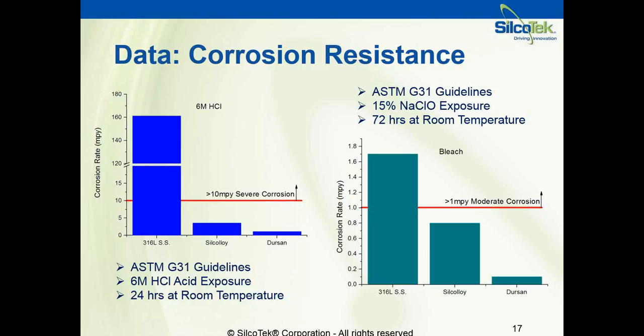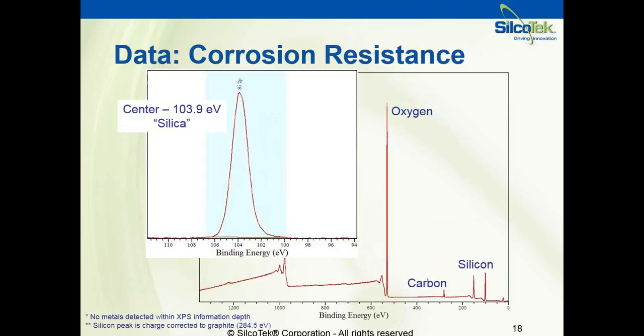And you can see that even the Silcoloy coating that we offer gets close to the moderate corrosion level. It's still within, but it is close to moderate corrosion, but the Dursan coating is significantly improved due to its material characteristics. And these are similar to what you would receive with a Dursan coating, so you can expect similar corrosion performance, at least with bleach.